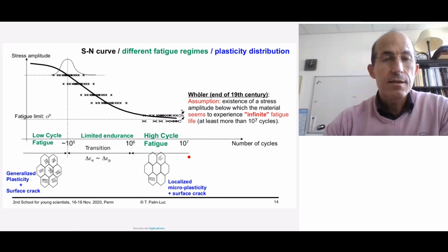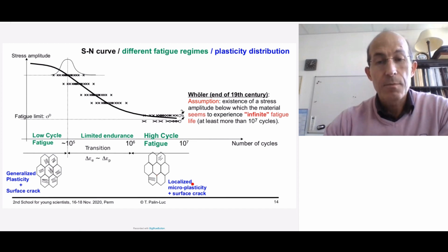This can be summarized in an SN curve, depending on the different fatigue regimes, by the following scheme. In low cycle fatigue, macroscopic plastic deformation exists everywhere in the material. Consequently, there is generalized plasticity. Each grain is plasticized, so there are persistent slip bands or slip markings everywhere. This is a regime of low number of cycles to failure. Then there is a transition. When you decrease the stress amplitude, there is a transition between macroscopic plasticity and elasticity. In high cycle fatigue, macroscopically, the material is elastic, so plasticity appears at a micro scale. It means the slip markings are localized in a few grains at the surface and are due to persistent slip bands. The crack initiation appears in intrusions located at these bands.